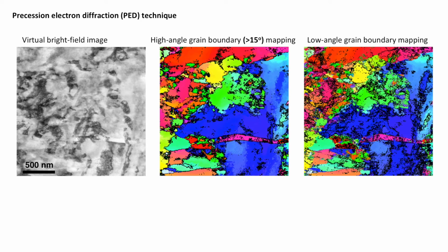One thing that really surprised us was when we saw the orientation mapping results. When looking at the orientation maps, we don't see these individual grains anymore. Instead, we see much coarser grains in the micrograph. The figure in the middle highlights the crystal orientation as well as high angle grain boundaries in the shear band. Here, we don't see these small nanoscale crystals anymore. But when we turn on the low angle grain boundaries, we start seeing these small crystals again. For example, like here and here.